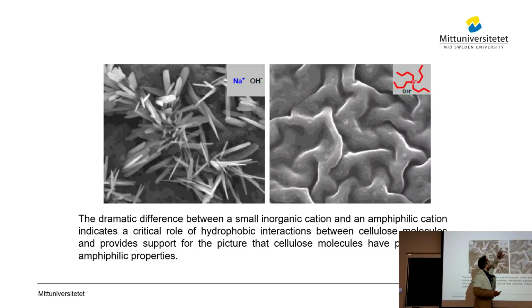And one way to show that, for instance, is to compare two alkaline-based solvents: sodium hydroxide, with a small inorganic cation, sodium, and tetrabutylammonium hydroxide, where you have this amphiphilic-like cation. What we observe is that that system is much more efficient in terms of dissolution, and we have an amphiphilic-like cation that is dissolving better an amphiphilic-like molecule such as cellulose. Of course, this is to make a long story short, and you also see differences in terms of regeneration, some kind of crystalline structures staying, which we believe indicates that the dissolution is not as good as in the system where we get something smoother. We have backed the data with different techniques and so on. But the message is that amphiphilic-like solvents might help in the dissolution process.